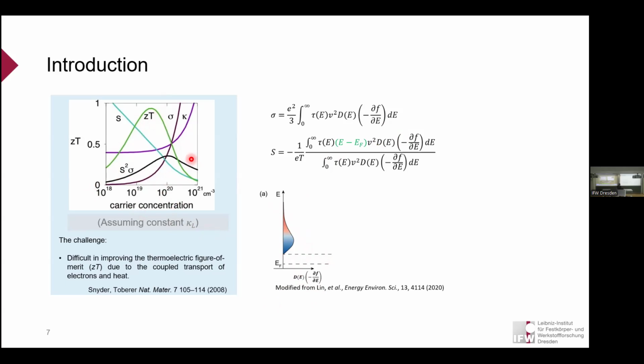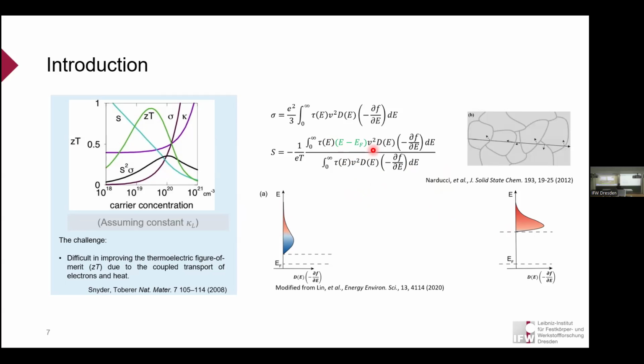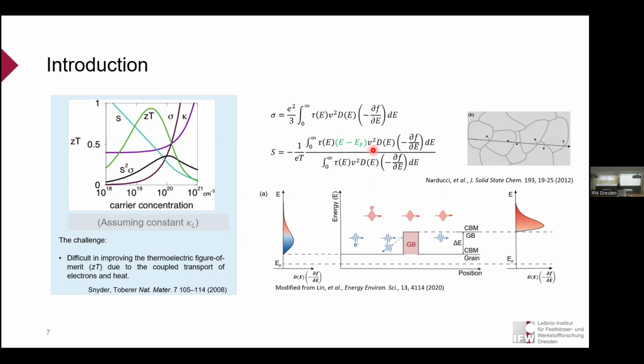In order to break this limit and get a higher ZT, an alternative way is, instead of playing with the charge carriers from the top of this window, to figure out a way to play with the bottom of the window. This way we could effectively increase the term E minus EF and have a higher Seebeck coefficient. This could be realized in real materials because there are a lot of grain boundaries, which could serve as scattering centers to scatter the lower energy charge carriers, enabling higher energy charge carriers to be transported while blocking the low energy ones. Of course, this is a simple physics picture of the energy filter effect.